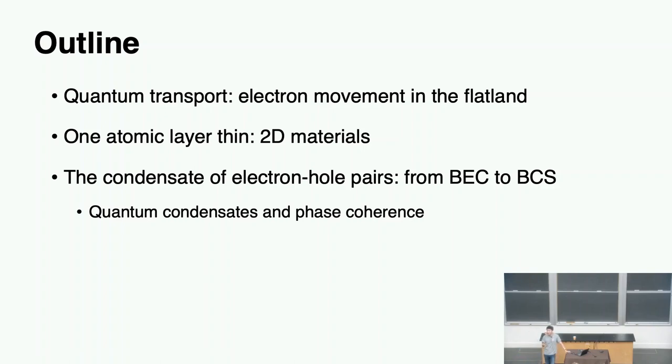We've tried other types of tapes. The answer is yes and no. You can do the Scotch tape method and produce the highest quality material, but they are tiny, and you cannot build a computer based on that. A different approach is to grow an atomic layer with chemical vapor deposition or epitaxial growth, but the problem is it depends on the substrate and crystallization, and you will have lots of defects. The two different approaches are trying to find a happy middle ground — it hasn't happened yet. So there's lots of work to do.